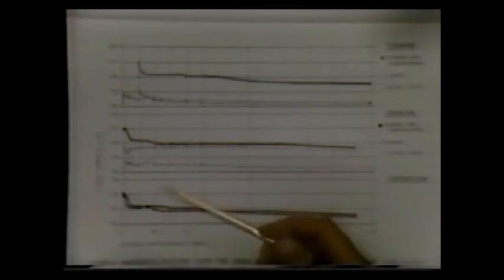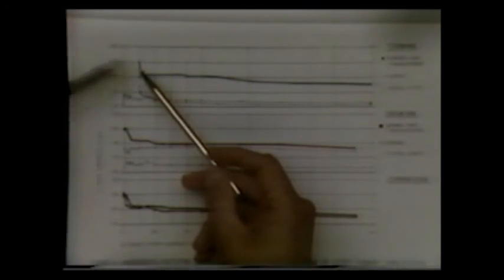If you have turning, that's the top diagram, the turning removes a surface layer of 40 thousandths and just work hardens a near surface zone to a depth of less than 20 thousandths. You can see it here. While straightening on the two-roll machine superimposes a work hardening effect which extends right to the bar core. The drawing, see it here, that's the bar core.